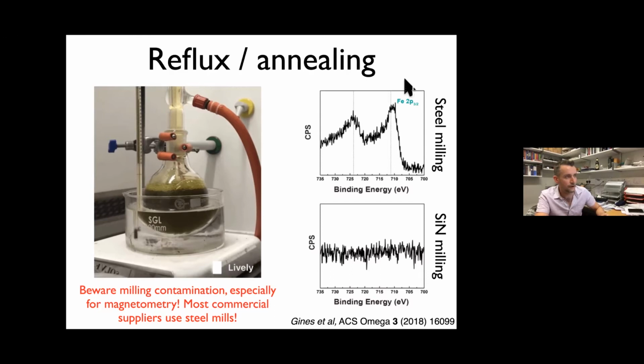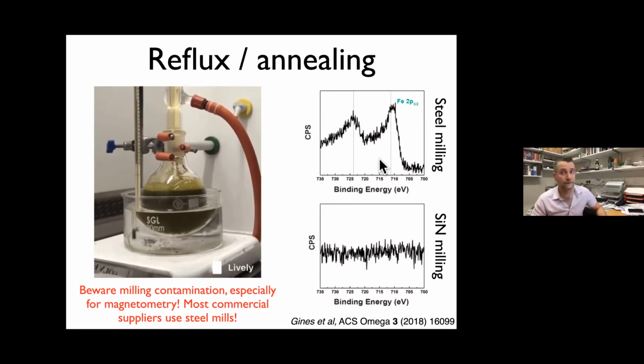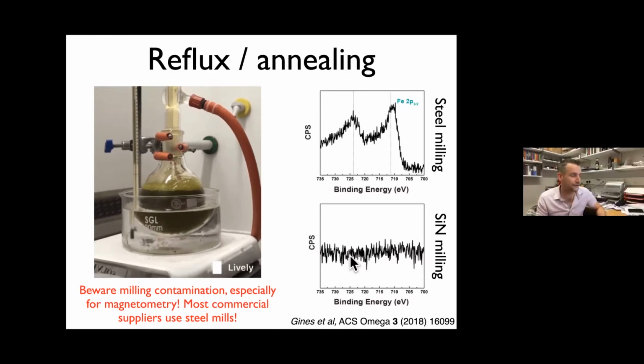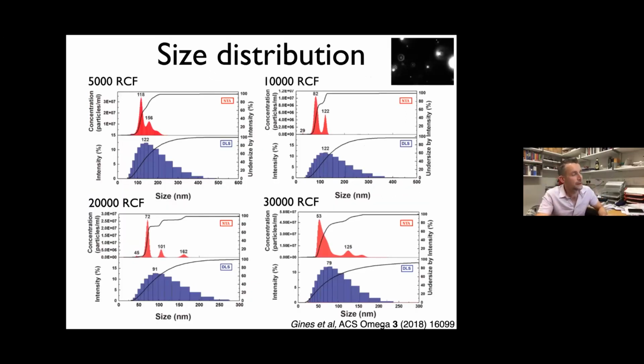And we did a lot of playing around, and we never got rid of it. Whatever we tried, we always ended up with something in the XPS. You can see here, this is the iron peak here, and it might even be iron oxide. I don't even know. I'm not a chemist, so I'm sure some better chemists can remove this, but we can't. We tried very hard. And so we kind of gave up and went to silicon nitride for certain applications. And this way we're able to get iron-free material. And I think is it the next slide? One second. Oh no, okay, in a couple of slides, I'll show you why.